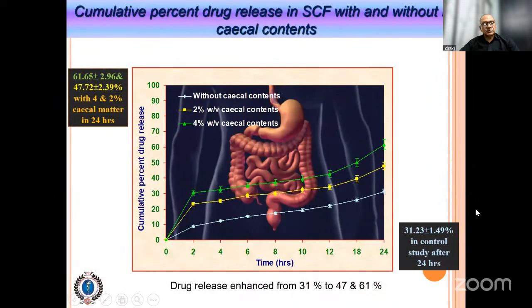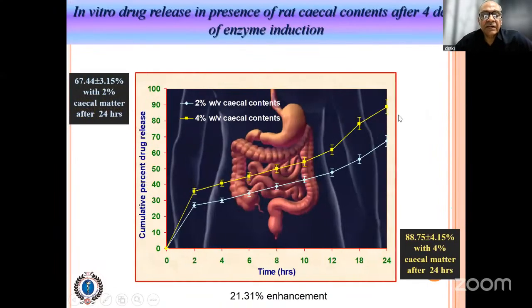Similarly, we perform different studies just to ascertain whether guar gum microspheres release the drug exclusively in the colon or not. So we perform different studies at different pH. Apart from that, we also studied the effect of the cecal content, colonic content, on the release of the drug. We observe that on increasing the concentration of the cecal content in the dissolution media, the release of the drug from the guar gum microspheres increases from 31% to 47% and 61%. So we observe mostly a 16 to 30% enhancement in the drug release if the cecal content is used in the simulated colonic fluid.